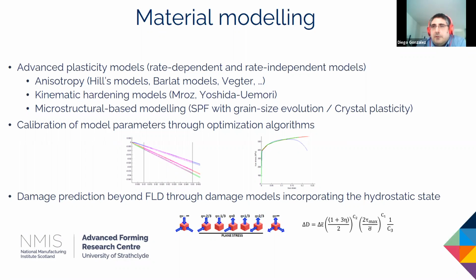We need accurate estimations of the parameters of the model, and when we talk about damage prediction, we also have expertise in this type of models, which evolve a damage variable for each individual element of the simulation to determine when we are going to have fracture. This is a line of research within the group, and we have colleagues working on this type of damage models. This approach goes one step beyond the forming limit curves. In many occasions we define the damage variable using the stress triaxiality factor.